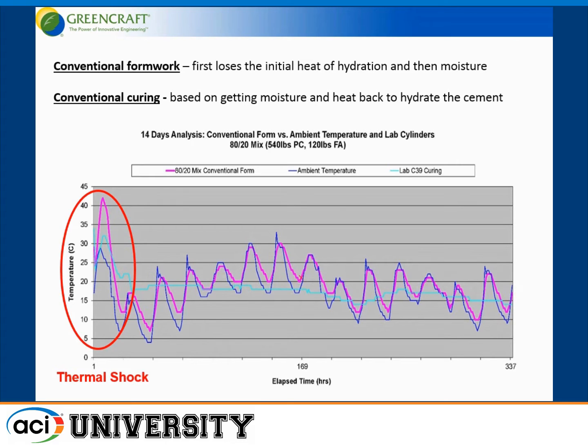And then immediately, typically overnight, you start dropping the temperature through the heat loss of the form. By the next morning, about 24 hours after placement, you reach ambient temperature. This is the red graph line. The dark blue line is the ambient temperature. The light blue line is the C39 lab cylinders of this mix. So we have this thermal shock at the point where the concrete has no strength to speak of, and that's where you get the nanocracking, microcracking, that later on turns into that surface cracking.